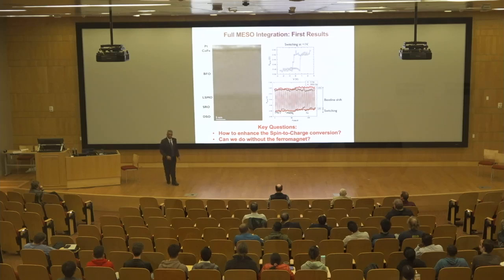Lots of issues with this. First, this interface between cobalt iron, which is the ferromagnet, and the multiferroic is a very bad interface. It corrodes very easily. So we were asking questions. How do I enhance the spin-to-charge conversion? Can we even do without the ferromagnet? So in the last 10 minutes, I will tell you a little bit about what we have done on this.